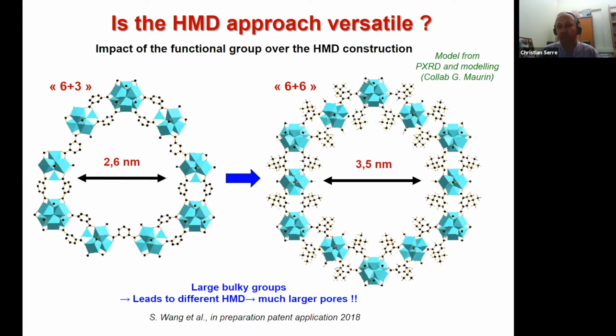We also recently obtained another example of this multivariate strategy. In the published result, we obtained the 6+3 clusters, let's say, so 3 Zr12 and 6 Zr6 clusters, by using isophthalic acid. And we realized that when we use some very bulky functional group like a tert-butyl, we obtain this structure where we have 12 clusters instead of 9, so 6 Zr6 and 6 Zr12. And as a consequence, despite the steric hindrance of the butyl group here, we increase the pore size by almost 1 nanometer, and we almost double the pore volume of the sample.